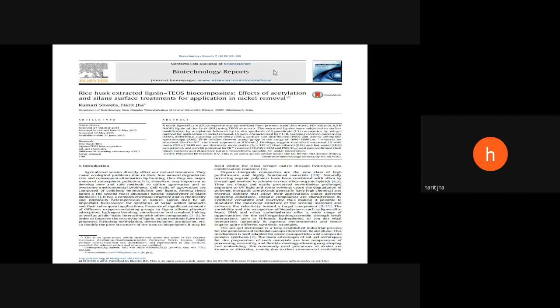In the next experiment, we have used the rice husk extracted lignin. I was talking about rice, that rice can also be used for extraction of many different useful components. For example, the rice extracted lignin and TEOS biocomposite have been used for seeing the effect of acetylation and silane surface treatment for application in nickel removal. This work was published in Biotechnology Reports, a good journal.